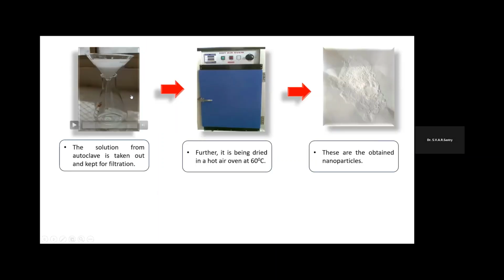Then the solution coming from that is transferred and kept for filtration. Then it is further dried in a hot air oven at 60 degrees Celsius. And then finally, we have this white powder obtained, the nanoparticles. This is of zinc oxide.